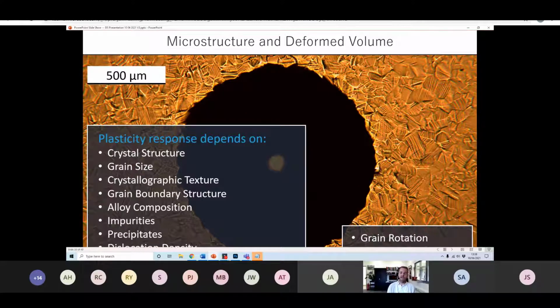Okay. And in fact, some of those microstructural features that I'm talking about are listed in this slide, and they include things like the crystal structure, the grain size, texture. Grain boundary structure is really important to macroscopic stress strain behavior. Full alloy composition, impurities, the presence of precipitates, what is the dislocation density? All of these things contribute to the behavior that you see in a macroscopic tensile test. So you have to interrogate that with your indent.